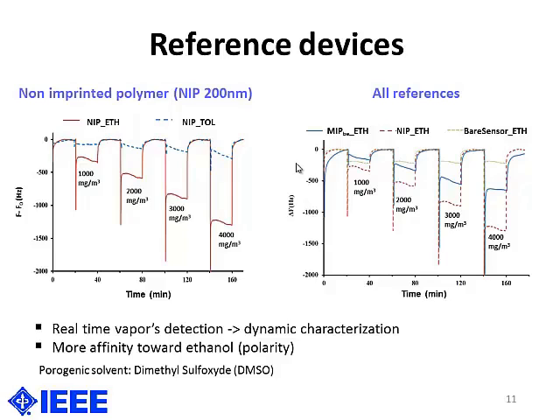And this second figure represents the real-time responses for three devices which could be investigated as reference lines. In fact, the same NIP-coated device in red. This one in green is a bare sensor, and we can see the same response whatever the ethanol concentration. And the third one is a MIP-coated device, but the MIP is before extraction of the compound, so the first step of preparation, and we can see that there is a response, and this is a response due to the porosity, but with the non-specific porosity in fact.